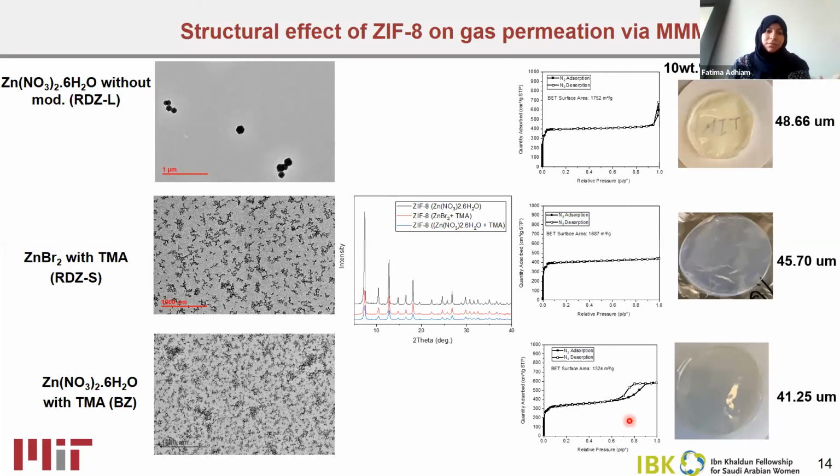No, the same conditions have been used for all of these 3 materials, but the behavior of the material, the presence of mesoporous material here within the branched ZIF material, indicates this. Actually, the pores here are interconnected pores because of the agglomeration of the smaller particles, and this would lead to this kind of behavior.